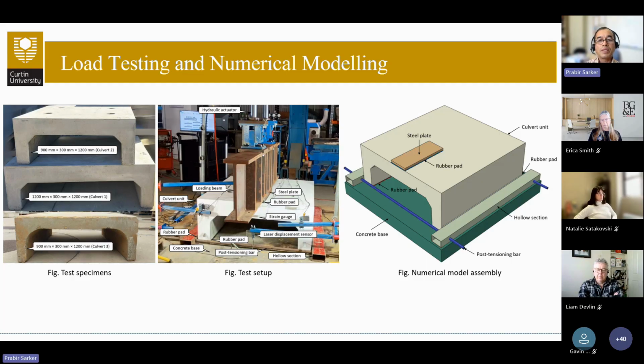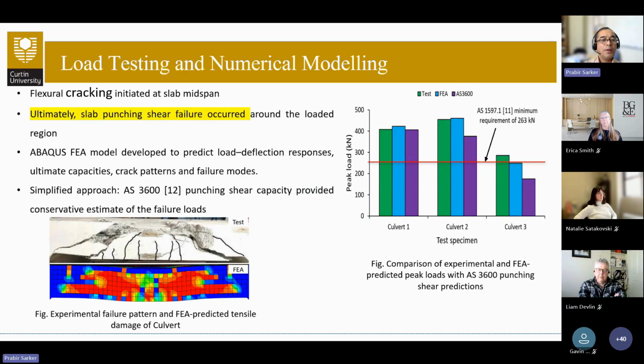This shows the testing of the culvert according to the Australian standard. What was found in all these culverts is that failure finally occurred by punching shear of the slab where the load was applied. The application of the load was a concentrated load on one of the sides in the mid span, and we see here a typical failure by punching shear. This is where the load was applied.